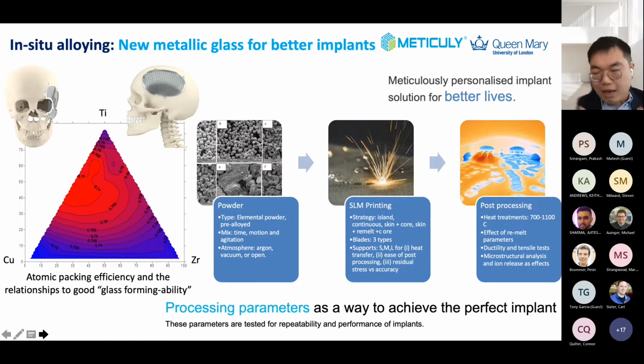So I'll give you an example of what we use at the moment for in-situ alloying, mixing them together under the beam, for a new metallic glass composite for better implants. As you know, traditionally, and what we all use now, is titanium 64, a medical grade, used for biomedical devices. And we have a project under the support of the Royal Academy of Engineering to explore another territory in terms of the material-process system, where we can improve this. So we are looking at a partnership with Thailand, looking at a titanium-copper-zirconium system, where we want to get the processing and the chemistry right to achieve the perfect implant at the end of the day.